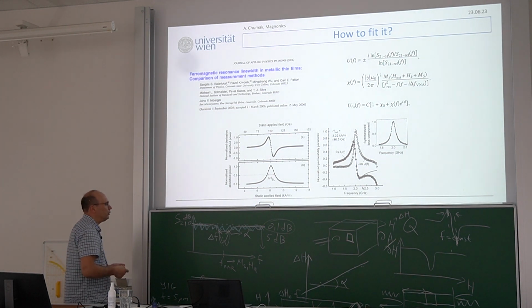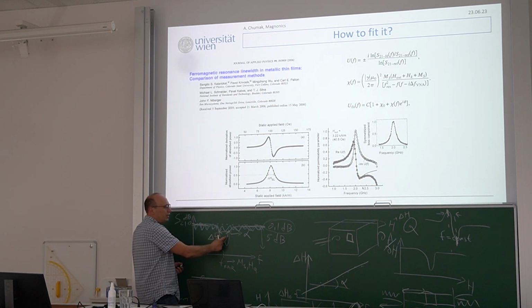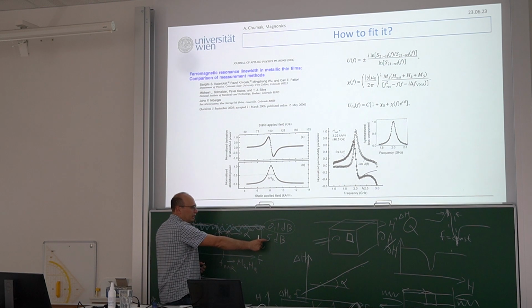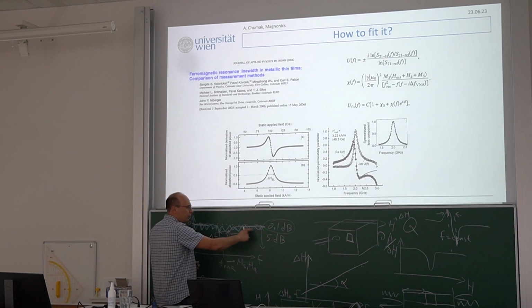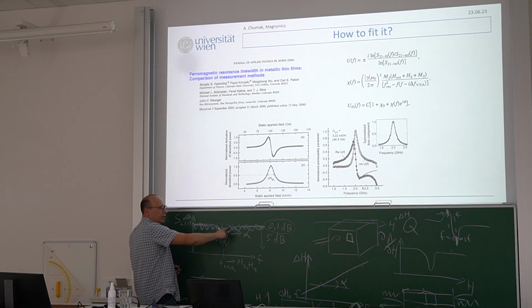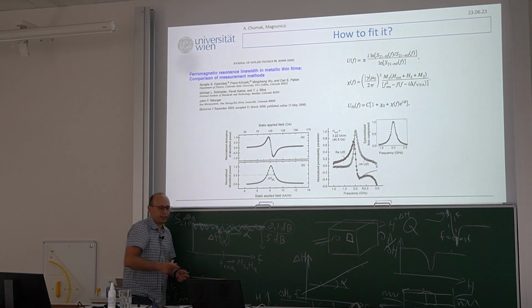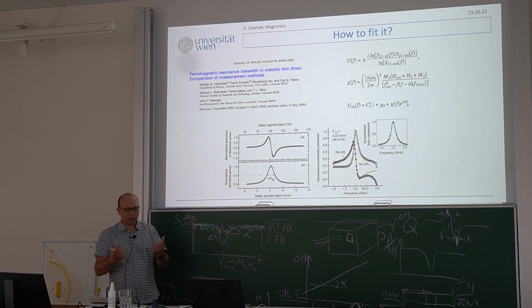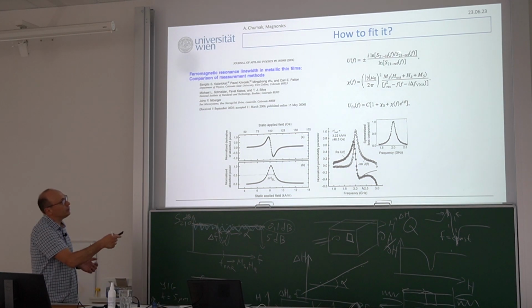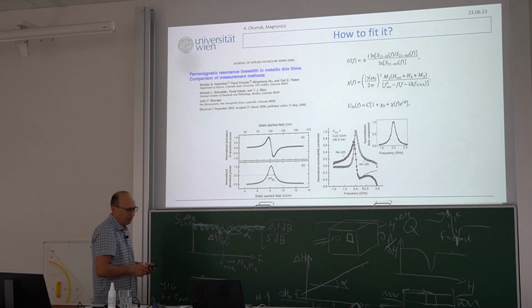Therefore, when we perform careful measurements, we slightly change the field, I don't know, 50 millitesla or 20 millitesla, shifting this peak just outside to make sure the background stays the same. Then you take a reference. Then you put your field back to this position. You have two signals, and then you can use this formula with the reference and this peak in order to subtract one from the other.